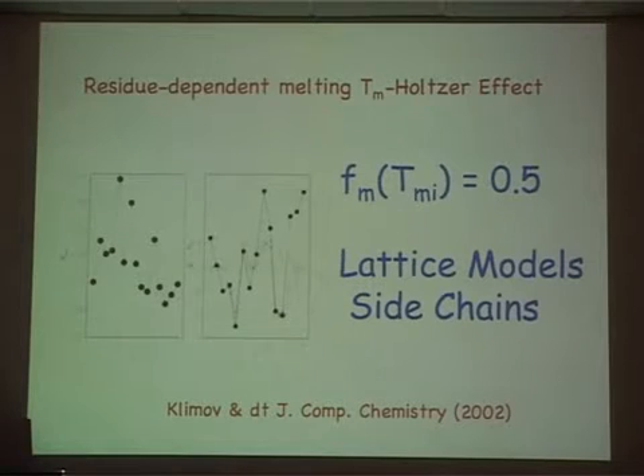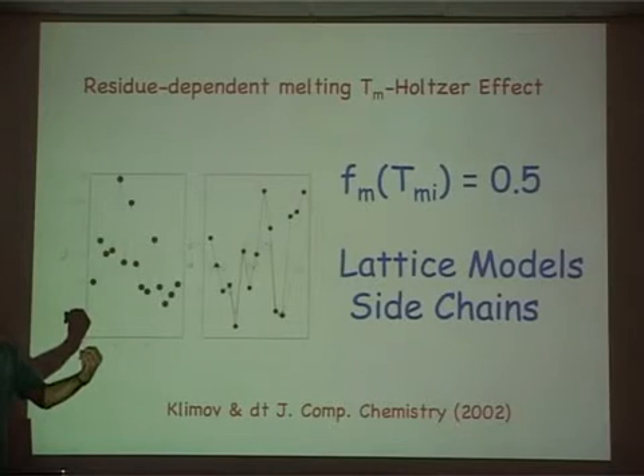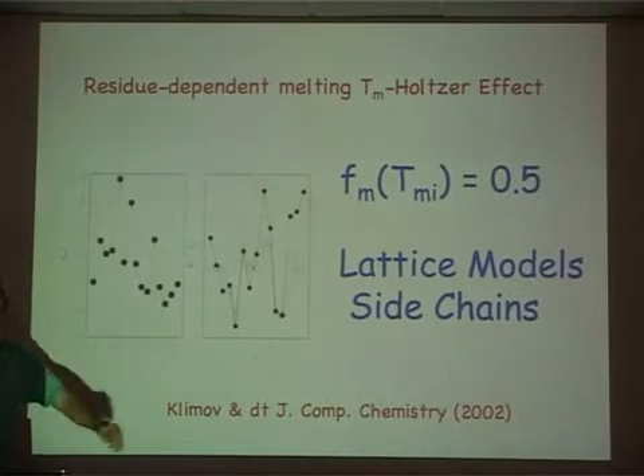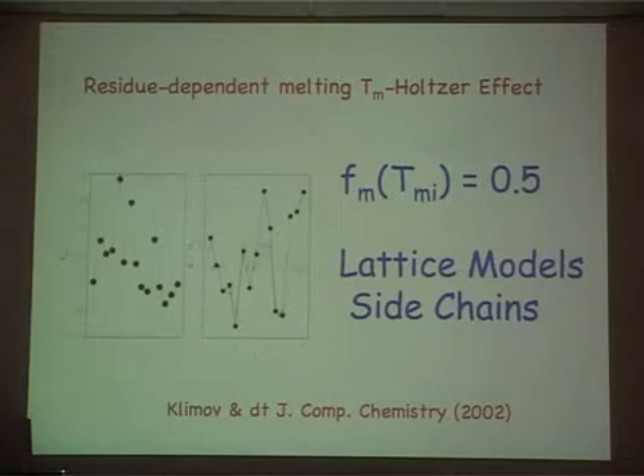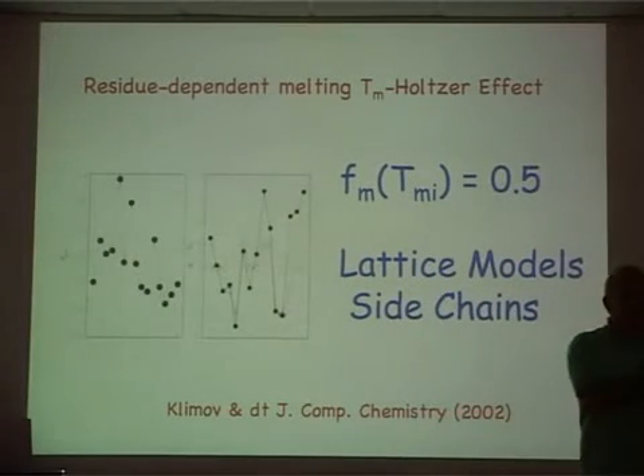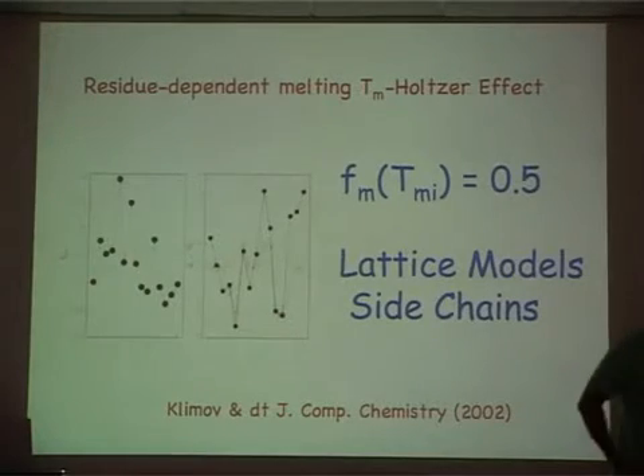Let me tell you what this is. This is just a lattice model with side chains. This is in this paper, and we looked at the temperature at which every single residue in this lattice model, it can be very precisely done, orders. Okay? And that is the temperature at which the fraction corresponding to the ith residue is equal to 1/2. So half the time it's fully ordered, half the time it's fully disordered. That's the melting temperature of that particular residue. Because in the native state, I know that this particular residue makes contacts with its neighbors and so many of them, and if it does it 50% of the time, I assign that. And that's how it's done in the experiment as well, roughly speaking.